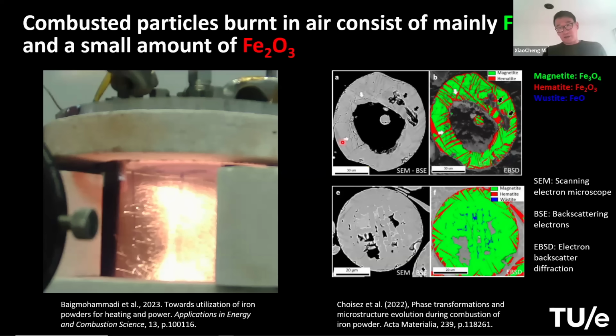And what I said, after the first few cycles, you do see some larger fluctuation, and then it gets stabilized. This is mainly due to impurities. Impurities can also give you a cavity. For example, if I have carbon or sulfur, these are volatile impurities, and during this high temperature oxidation, they will form a gas phase product. Even if the impurity mass percentage is very low, because of the low density of the gas product you can still make a big bubble inside the particle, and sometimes it can also cause what we call a micro explosion, right? Basically it shatters the particles. Yeah, this can happen, but this kind of phenomenon can go away after the first few cycles, because the combustion is actually purifying, removing these volatile impurities. Okay.